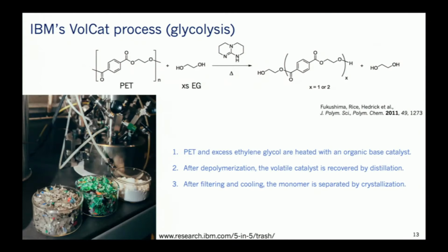So starting with the first type, the condensation polymers, which generate small molecules when you make them, you can drive these backwards with a suitable catalyst. And this process from IBM, the Volcat process, is a very nice example of that. The polyethylene terephthalate, even as mixtures, even as these dirty post-consumer waste materials that contain other components, can be cleaved by the presence of excess ethylene glycol, which is one of the monomers used in its synthesis to begin with, in the presence of a suitable catalyst. And in this case, the catalyst is a volatile organic base, which spontaneously separates from the reaction mixture after the process occurs. And you get these monomer components, or fragments, that can then be repolymerized. And the chemical purification of these products is quite straightforward.